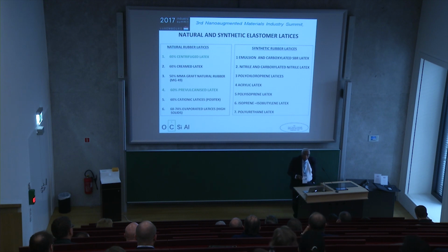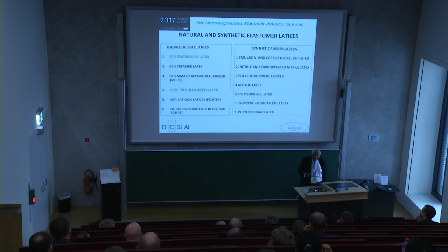We have also reverse charge latices, where natural rubber is an anionic latex, but we have the process of converting it into cationic latices. And that's useful where we are working with different substrates. We want better adhesion, so we use the available cationic natural rubber latices. And then there are the evaporated latices, where we spray the latex and vacuum evaporate it and raise the concentration from the average level of about 60%. We can go as high as 74% solid material.